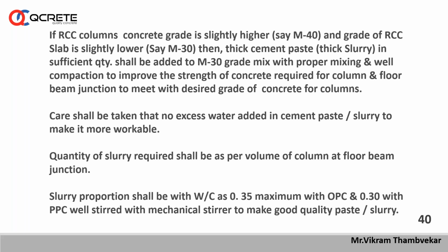And of course I have suggested these techniques to avoid a different grade of concrete being used for the column at the junction level itself. Care shall be taken that no excess water is added to the cement paste or slurry to make it more workable. Don't make it more workable, make it just normally flowable, so that you can pour it properly into the junction, or you can mix it with the lower grade concrete. These techniques will definitely help you improve the quality of concrete at junction level, and of course it will give a good finish, no honeycombs, no porosity in that particular area, because many times there is a junction with very congested steel. So proper compaction is a very important factor at the column beam junctions to place the concrete properly.